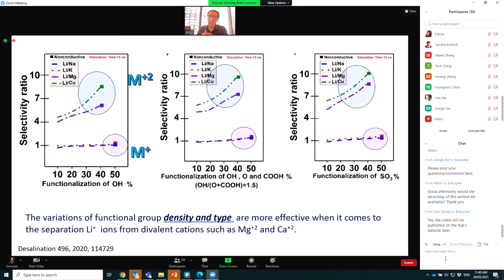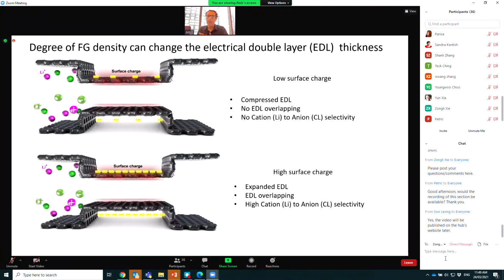We also found that variation in functional group density and type is very effective in separation of lithium from divalent ions. However, when it comes to separation of lithium from monovalent ions, for this particular case, it doesn't give us a significant change. The other contribution of charge and functional groups is through altering the electric double layer. We all know that if we have low surface charge, we end up with a compressed electric double layer, and we don't have EDL overlapping, and in that case your membrane doesn't show selectivity. Whereas if you have high surface charge, you will have electric double layer overlapping, which gives you high cation to anion selectivity.